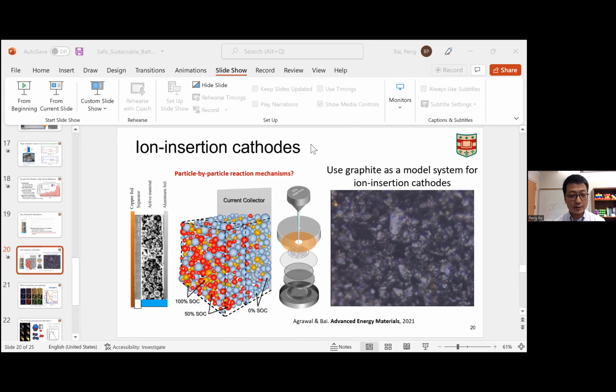You have different particle shapes, and some particles have good electrical contact, so electrons can come in, so ions can come in even more easily. Some particles don't have this good contact. Some particles have easy access to the liquid electrolyte. Some particles are not fully wetted by the electrolyte. But for this one, what we are focusing on is not a structural reason, okay? It is because of something more fundamental, related to something called the thermodynamics of the particle.